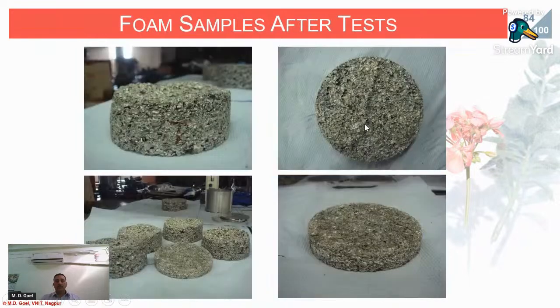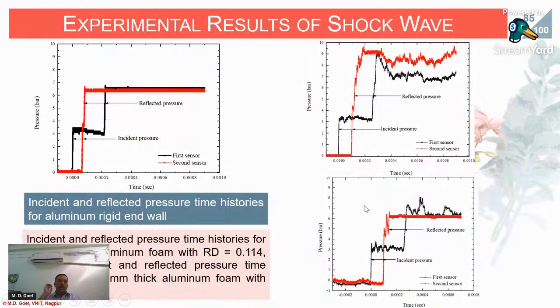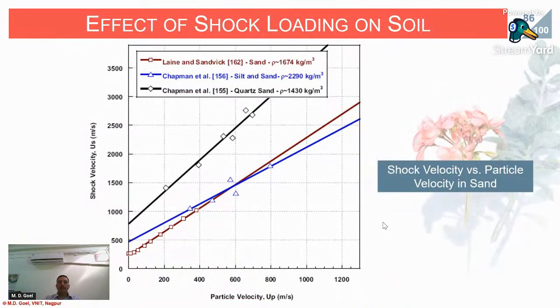So these are the foam samples before and after deformation, or partially deformed. Here you can see the thickness of the sample was 50 mm, and finally it was reduced to less than 1 centimeter after the test. So layer wise deformation and complete deformation were observed. Here you see the pressure versus time curves we got. We have an incident pressure as well as a reflected pressure for two sensors, and for different densities of foam. Here we can see that some of the pressures were higher, some lower, and with different types of foam we were able to calibrate the data on the behavior of the material.